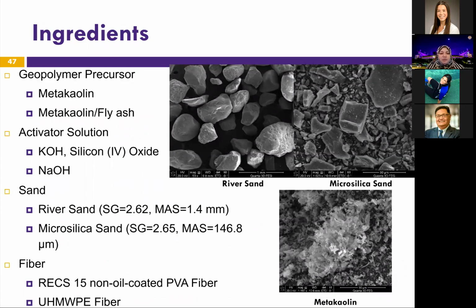So the ingredients that we used for that first project included the geopolymer precursor as either metakaolin or a hybrid between metakaolin and fly ash, and we used them as 50-50. The activator solution was potassium hydroxide and sodium hydroxide mixed with silicon dioxide. And we tested 2 aggregates, river sand and microsilica sand. And then we tested 2 fibers. We used the first fiber that we used for our ECC, which is non-oil coated PVA fiber. But that is still more expensive than ultra high molecular weight polyethylene fibers. So we wanted to experiment with these two.